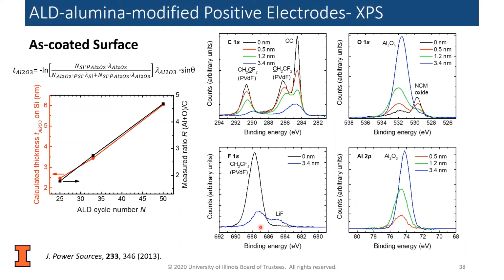And so one thing that surprised us, but after thinking about the chemistry a little bit, it shouldn't have surprised us, that we actually were coating the binder. But we realized that aluminum, probably in the trimethyl aluminum, is pretty reactive to the fluorine in the binder.